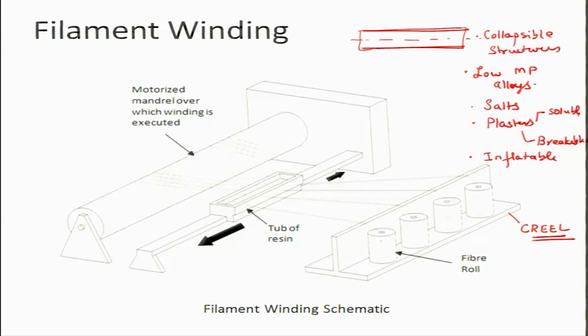So you have fibers coming from different reels, and they pass through a tub of resin, so they become wet, and then they are pulled by this mandrel which is continuously rotating. So the fibers wind around the mandrel, and as this is happening, this tub of resin moves back and forth. So you start depositing material along the length of the entire mandrel. In this way you can have an axisymmetric structure made up of continuous fibers. Here the trick is that you have to use continuous fibers.